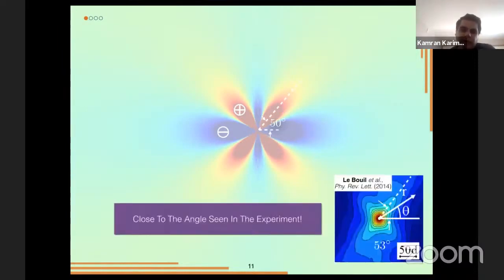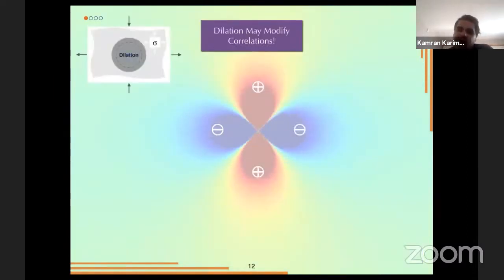And perhaps you have guessed by now that this is rather close to the angle that was seen in the experiment. We may also look at a dilational transformation zone, because in frictional materials, locally you might get dilation due to shear. For this dilation, the pressure field is trivial because it's isotropic. It increases pressure everywhere, so it won't have an effect on the angle of maximum Coulomb stress. But again, it can cause perturbation in shear.